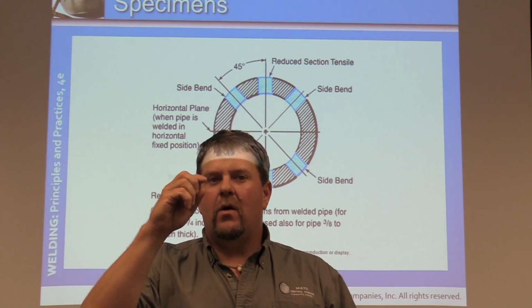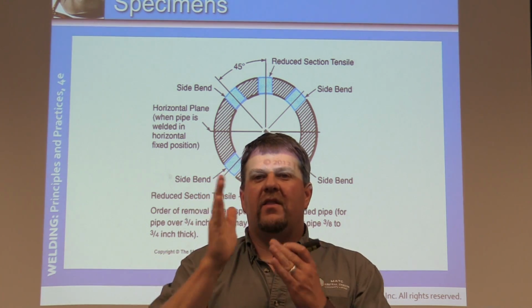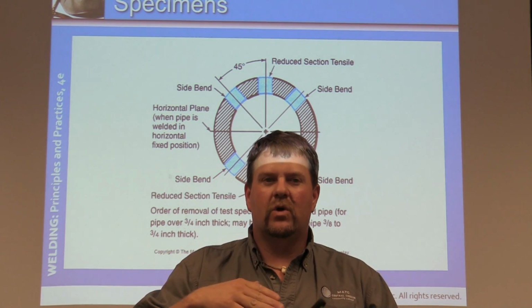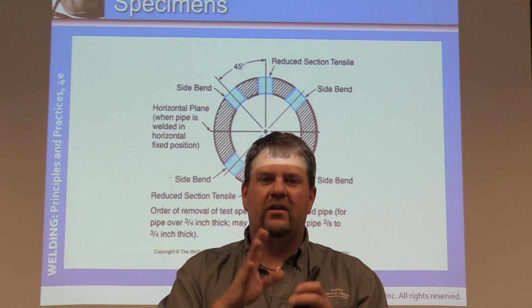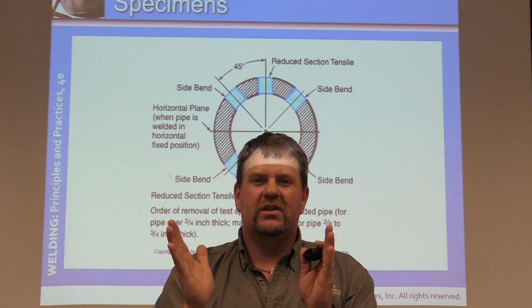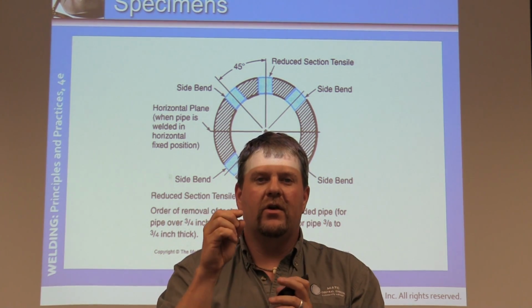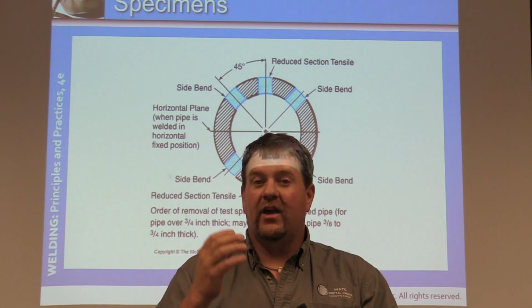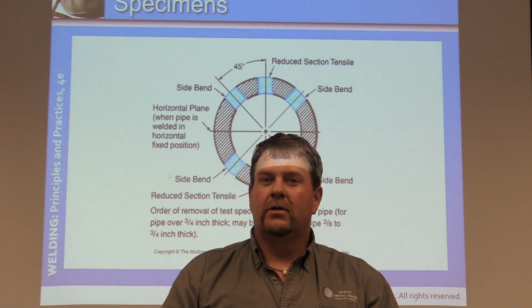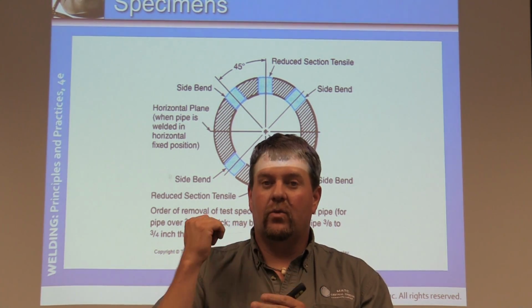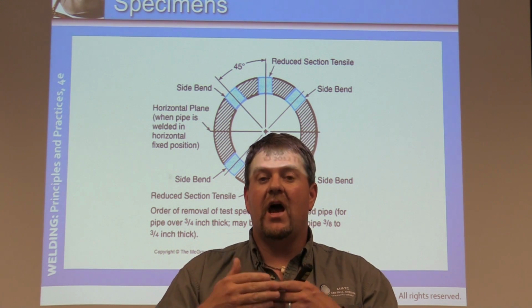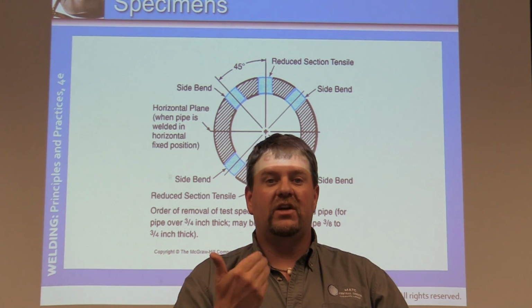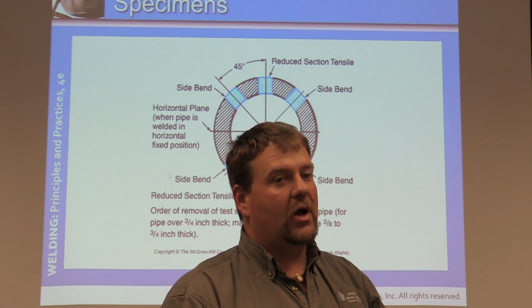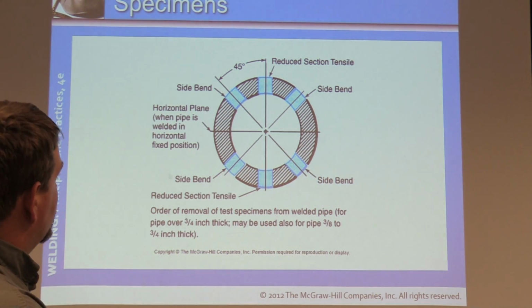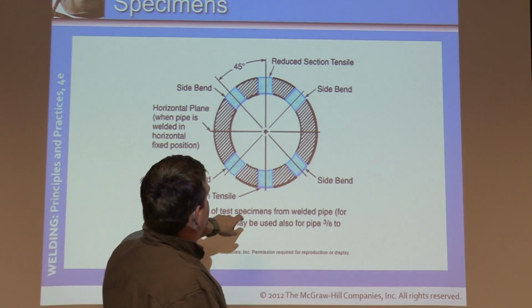Now the thinner the material, when we bend the face or the root, they've engineered it, they've spec'd it. You're going to see the discontinuities usually show up in the thinner material. Once you get thicker, they can be hidden, okay? So there's kind of like a cushion in there. So once you're above 3/8 of an inch thick, now we start doing side bends so that we'll see any interior discontinuities as well. Now this reduced section tensile, this is where we machine it down to a specified distance